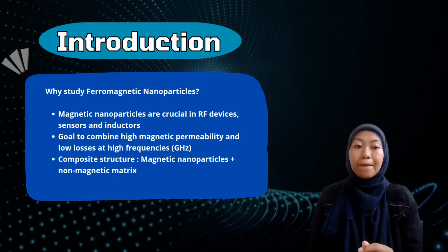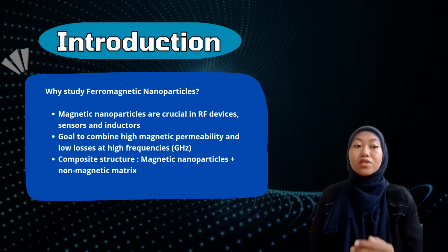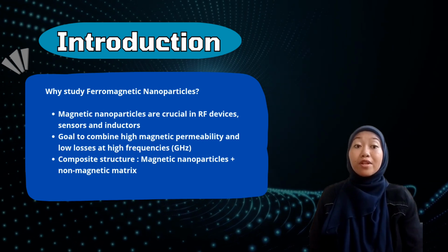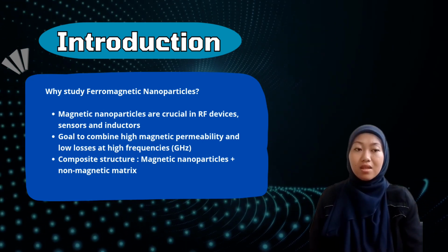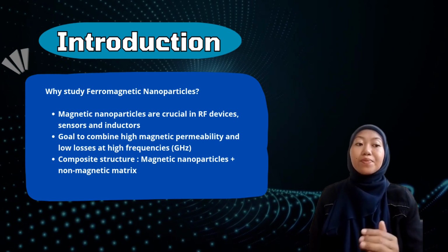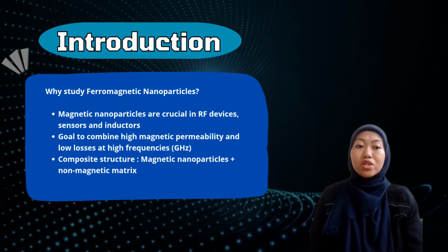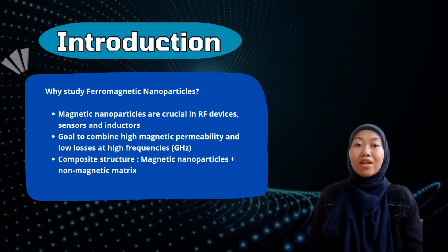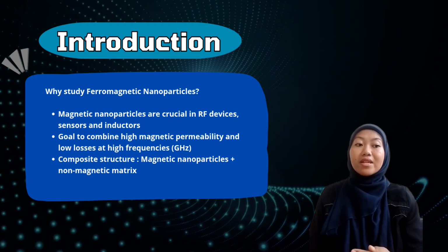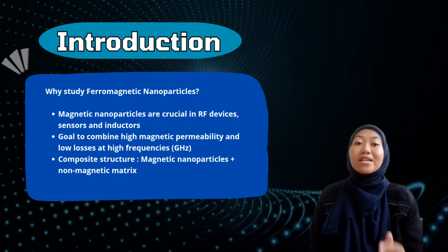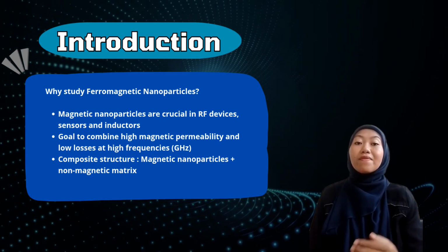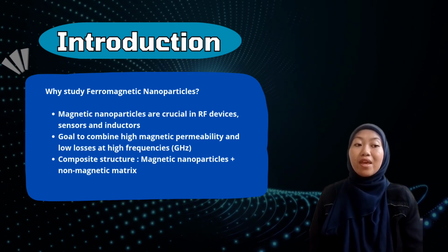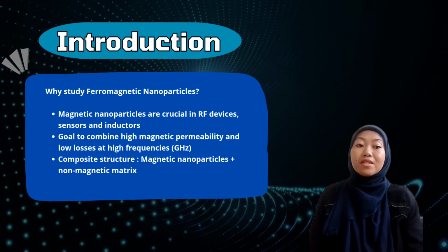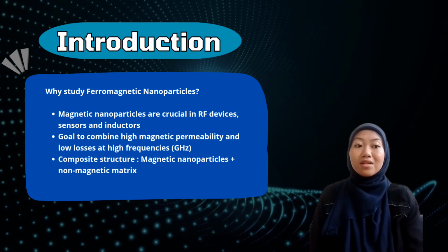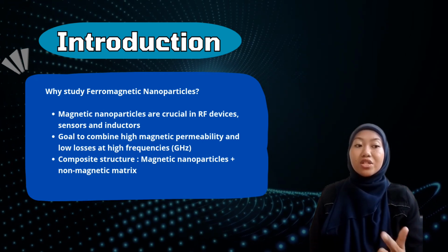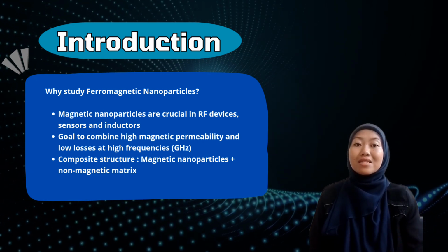Traditionally, thin films made of nanostructured soft magnetic material have been used to enhance inductance. However, this study explored an alternative approach using metallic ferromagnetic nanoparticles embedded in a non-magnetic matrix. These composite systems offer the flexibility to tailor magnetic behavior by adjusting the physical properties of the nanoparticles, such as their size, shape, orientation, and also distribution.